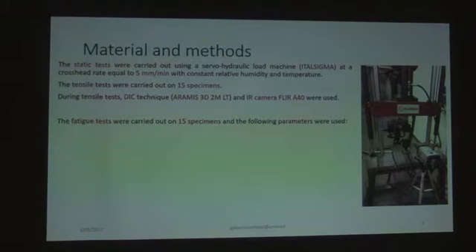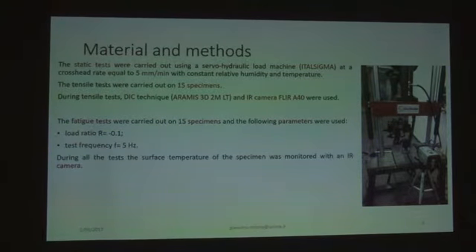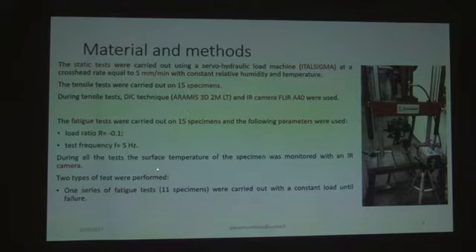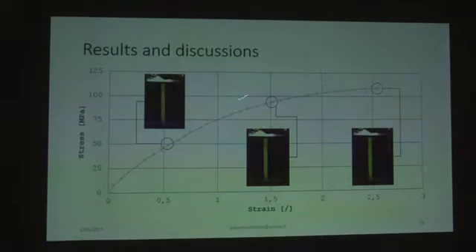The fatigue test was carried out on another set of 15 specimens with load ratio of minus 0.1 and a frequency of 5 Hz. During all the tests, we use the similar IR camera. The humidity and temperature in the lab are constant: the temperature is 23 Celsius and humidity 50%. Two types of tests were performed for fatigue test. One series for 11 specimens with the constant load, and for 4 specimens we carry out with the increment load step.